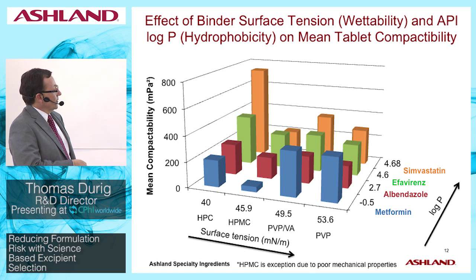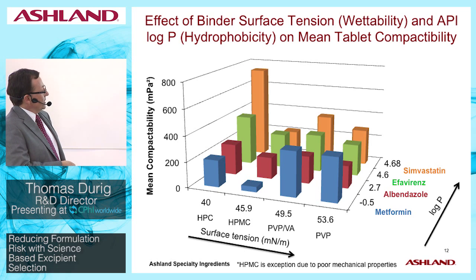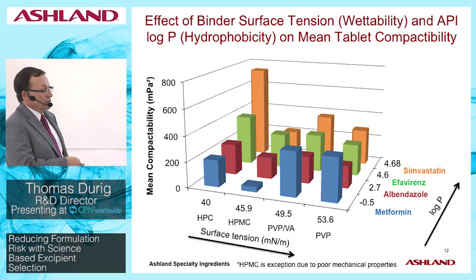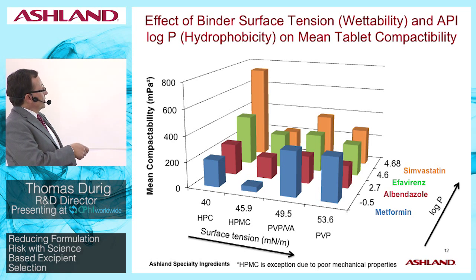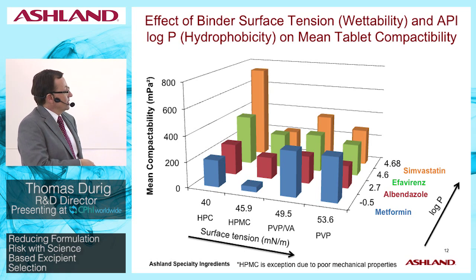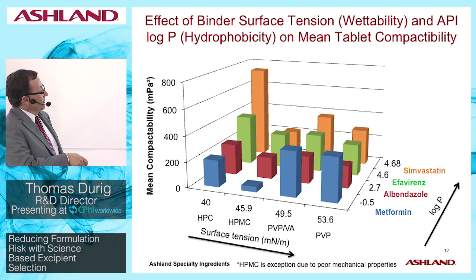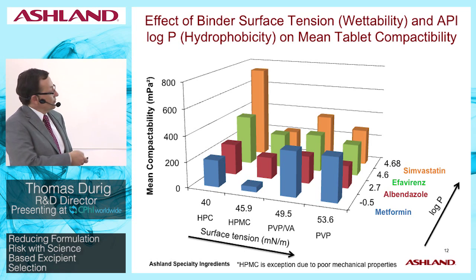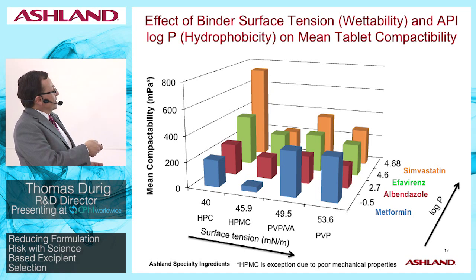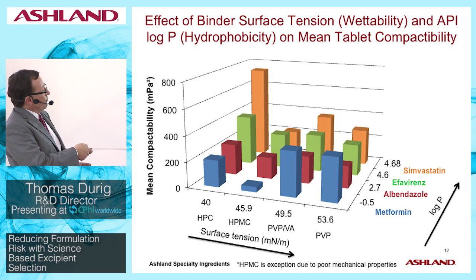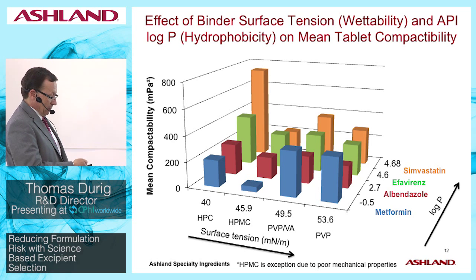And as you can clearly see here, for a low log P, so a very hydrophilic molecule such as metformin, clearly the PVP and copovidone, which have the higher surface tensions due to their more hydrophilic nature, give much stronger tablets in terms of tablet compactability as compared to the lower surface tension of HPC and HPMC. As we move up this hydrophobicity scale, we can see perhaps for albendazole, the red series, it really doesn't matter much in this intermediate hydrophobicity range. All the binders perform similarly, but then as we move up the chain here towards the more hydrophobic APIs such as efavirenz and simvastatin, clearly the HPC stands out as giving far more compactable tablets than the other tablet binders.